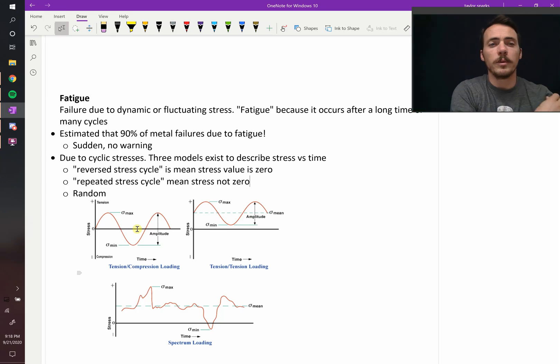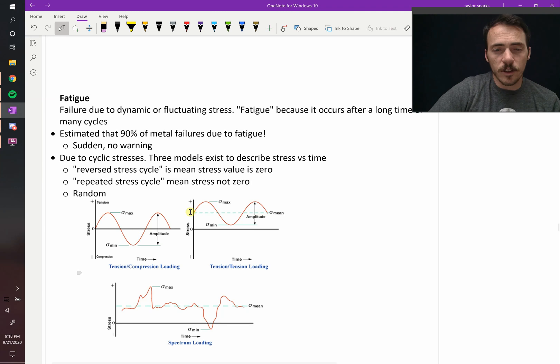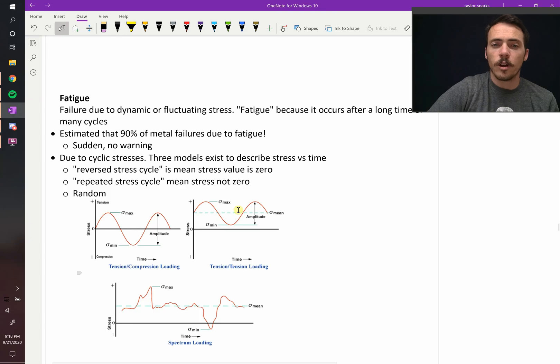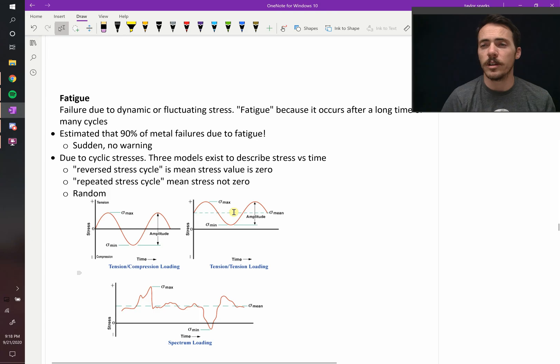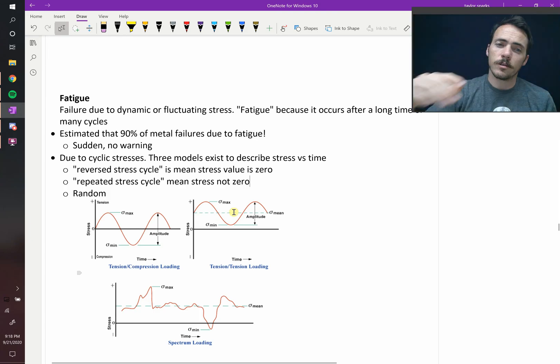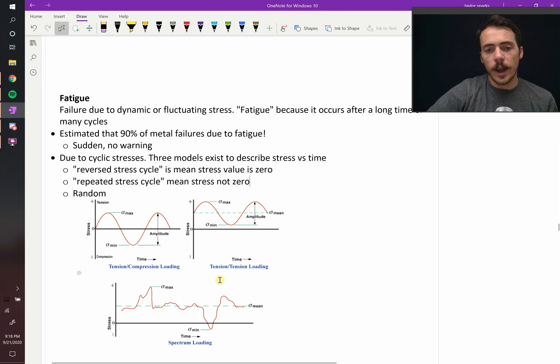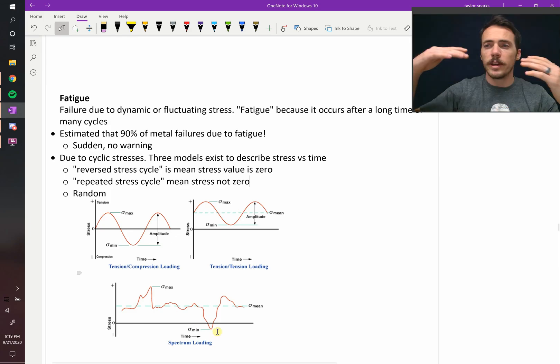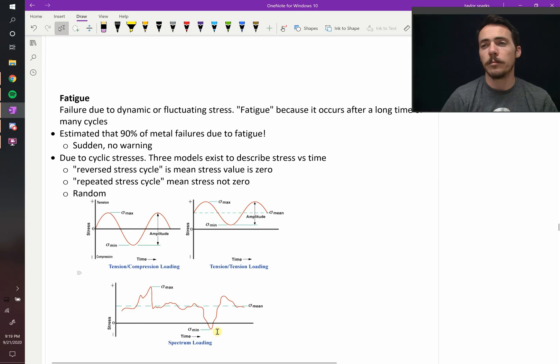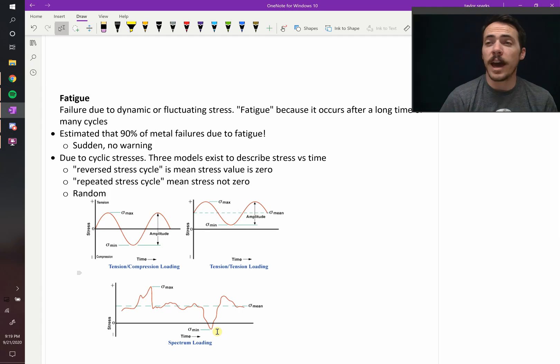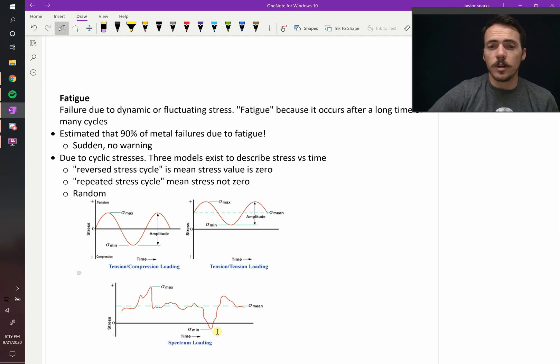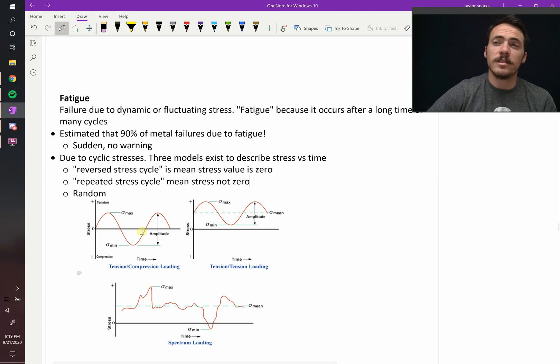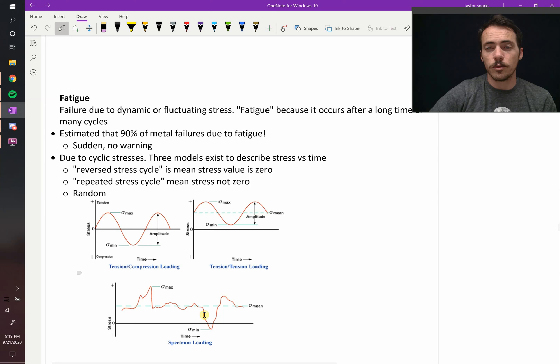Now another type of loading would be repeated stress cycle. Take a look at this one. It's alternating between a large tensile stress and a small tensile stress, large and then small. So at all times it's under tension, but it's varying in its load. And the last one would be random or spectrum loading where it's going up and down, but it's a random pattern. These can be, depending on your application, if you're talking about the fatigue in the axle of your car, it's going to be probably something like this if it's not just right. Whereas if it's say day and night cycling from thermal fluctuations, it might be more close to a random loading.